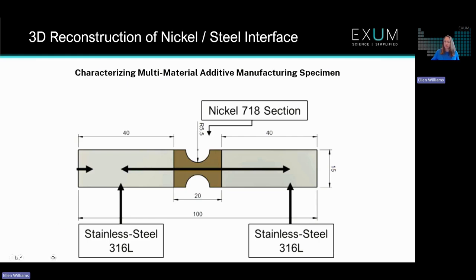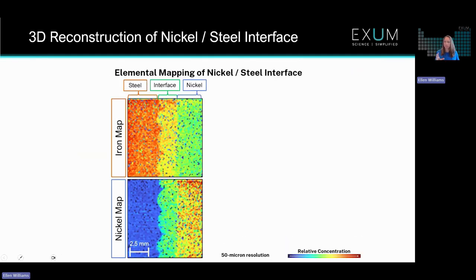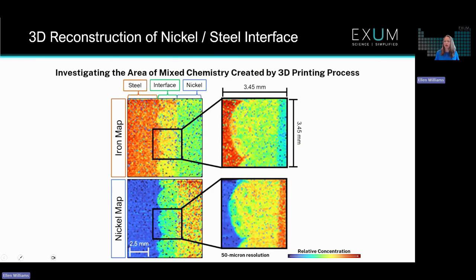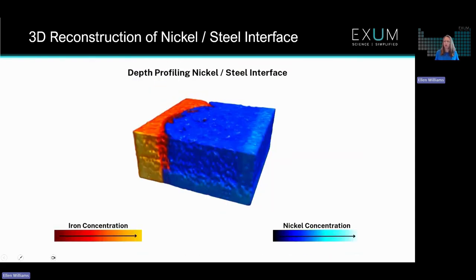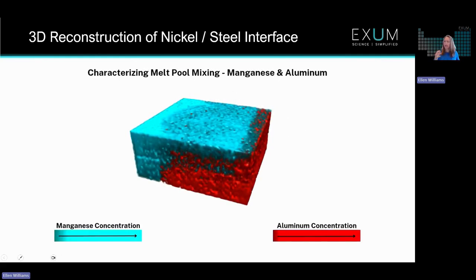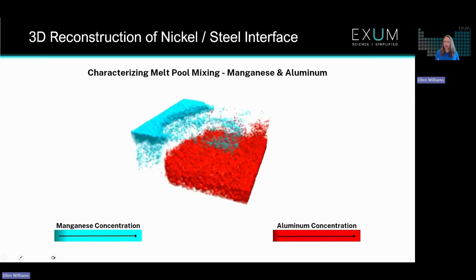But then the final piece here, just to show something that's easier to show in video rather than in static images in the paper, is what we did with a three-dimensional analysis. So I'm going to play this video and just show you that we analyzed an area across that 316L stainless steel to nickel alloy interface. And then we did a specific analysis right on one of those melt pool beads. So you can see we did an analysis on the melt pool bead, but then repeated that analysis so that we were getting a 10 micron deep depth profile.